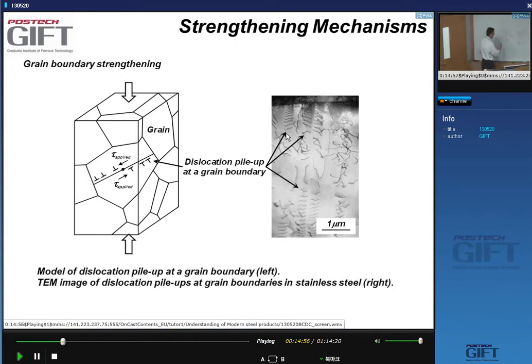The next dislocation that follows it is exactly the same dislocation on the same glide plane. Same Burgers vector, same glide plane. So they exert a very strong repulsive interaction on each other. So there is a repulsion. And the more dislocations I add, the stronger this repulsion is.